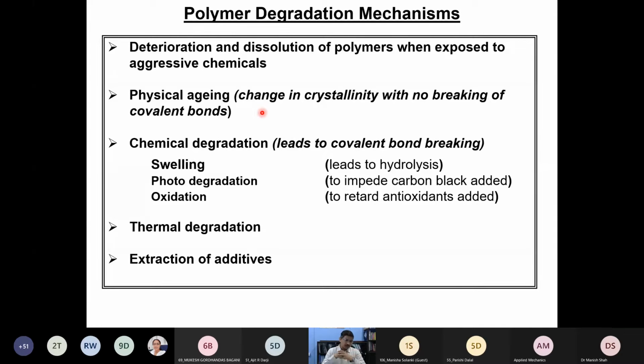And then if the polymer is exposed to high temperature for a long period of time, the best example is a landfill where a lot of organic waste is disposed of in the form of food waste or some other form. The readily biodegradable component in the waste degrades slowly, and over a period of time this degradation process causes a rise in temperature within the landfill. As a result, your geomembrane or the GCL may sometimes be exposed to high temperature for a prolonged period.